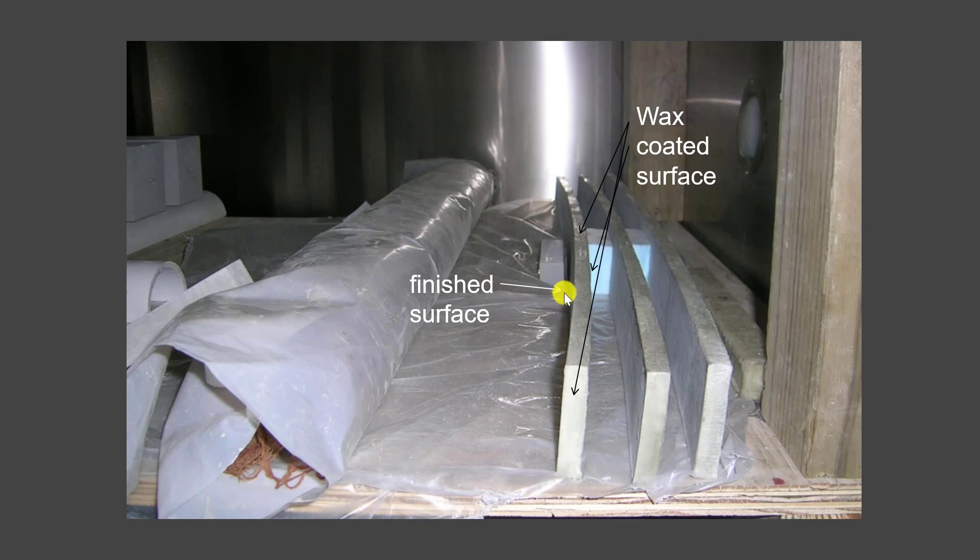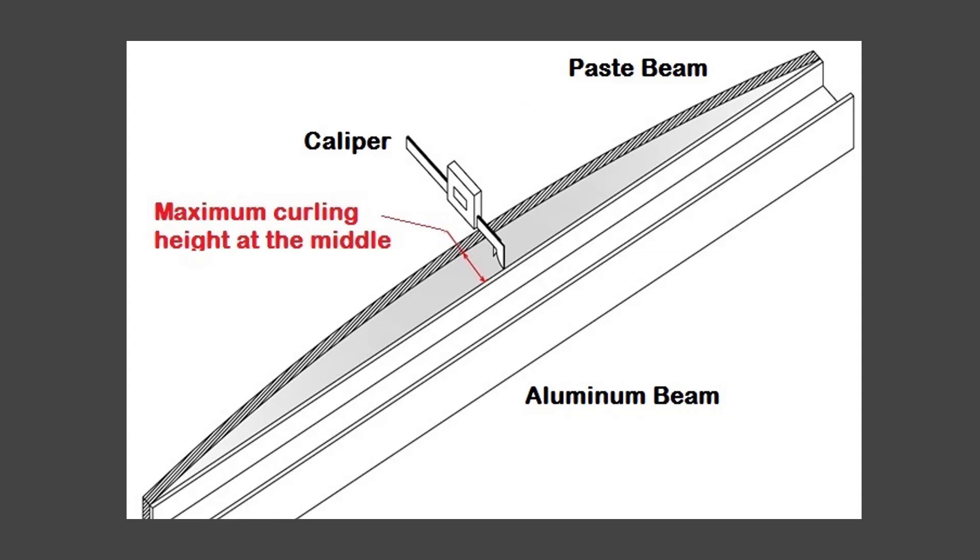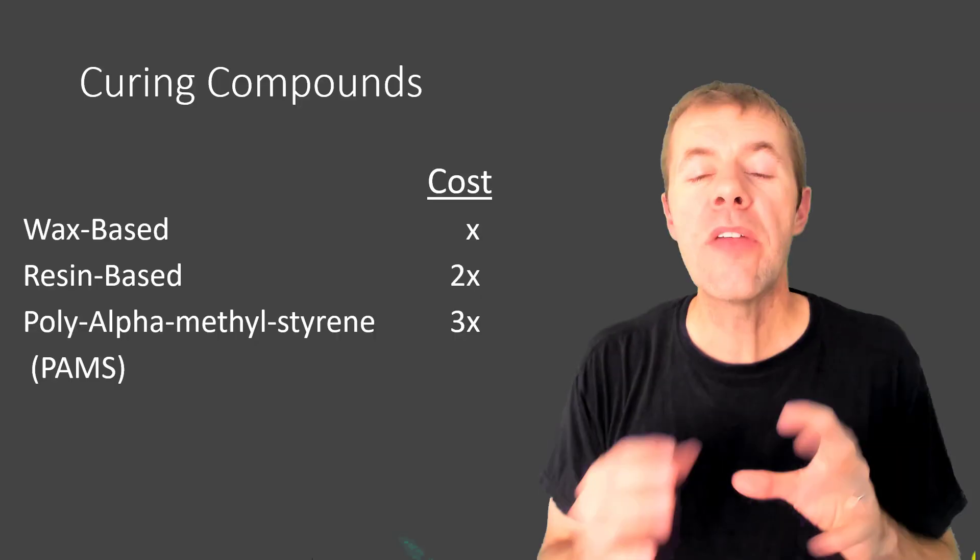Here's the finished surface on its side. This is where the curing compound goes. We have wax over here. Why do we do this? Because we don't want gravity to hold it down. We want to see how much it wants to curl. This is the max amount of deflection that we can measure at the center. We're going to use a caliper to do it.